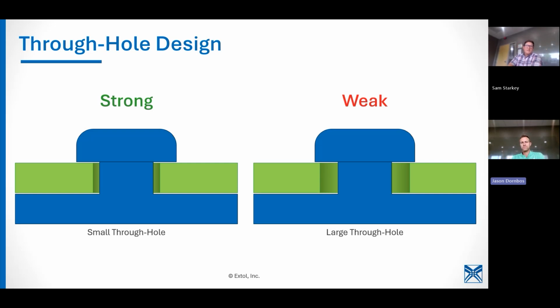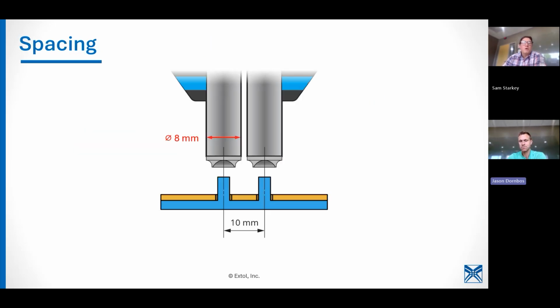Yeah. So with glass fiber materials, which we run into a lot, obviously, the shrink rate with flow versus transverse is quite different. So, to Jason's point, if you can use that to your advantage and tighten up that through hole in the flow direction because you're going to have less shrinkage, designing around that to try to get it as tight as possible is optimal. Yeah. But I think what we really want to communicate here is that a small through hole is ideal and it's very important for strength. Yeah. And we will flag that in the design phase as we're doing some of that work ahead of time to try and run through feasibility. We'll tell you your design is terrible if you have a big through hole.